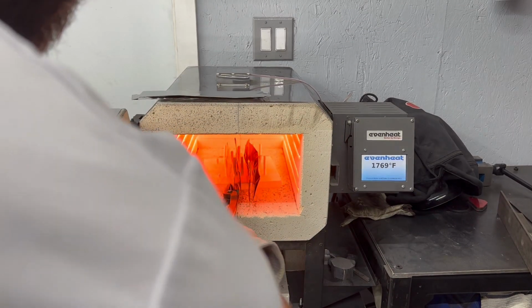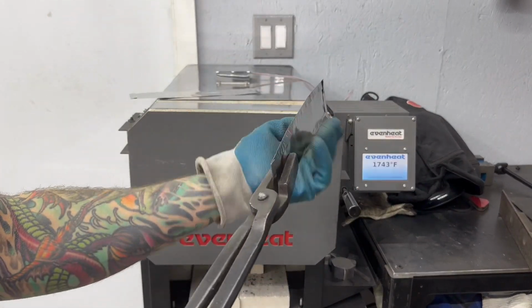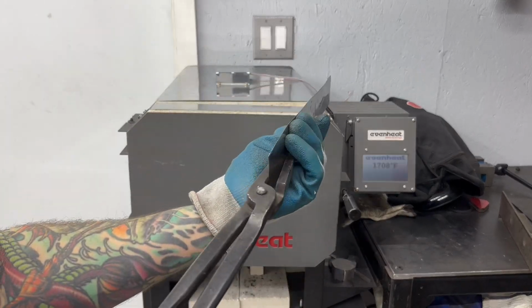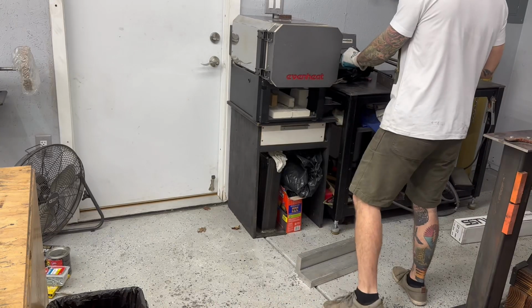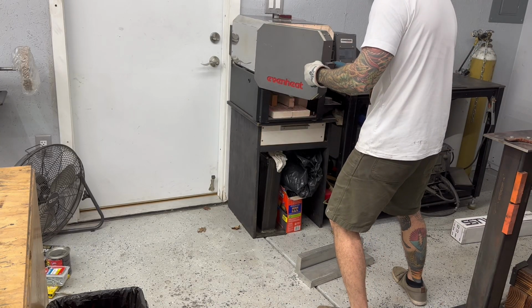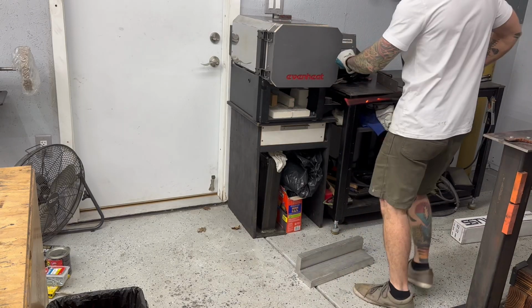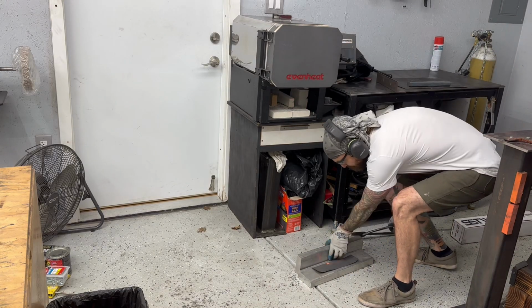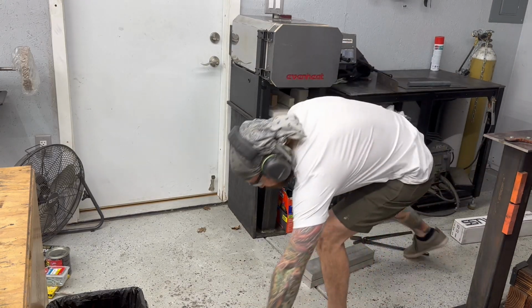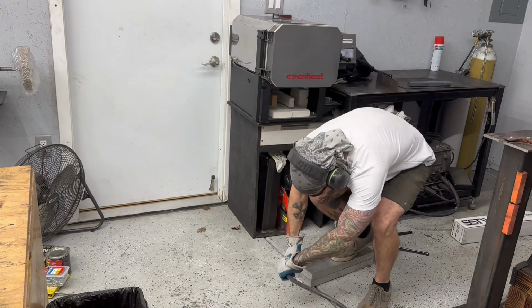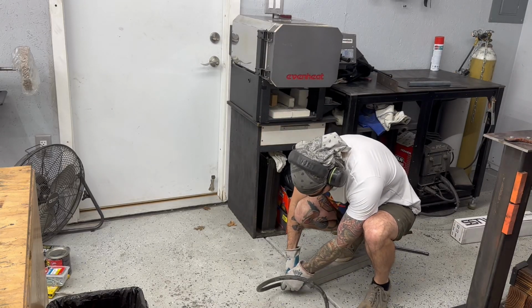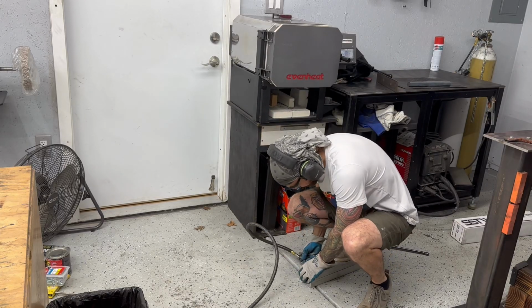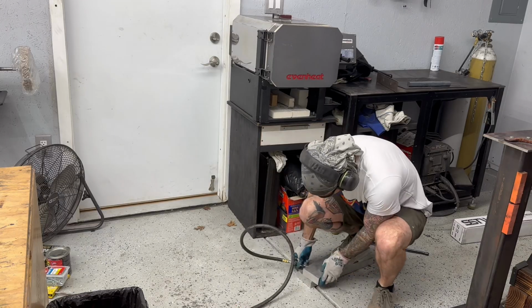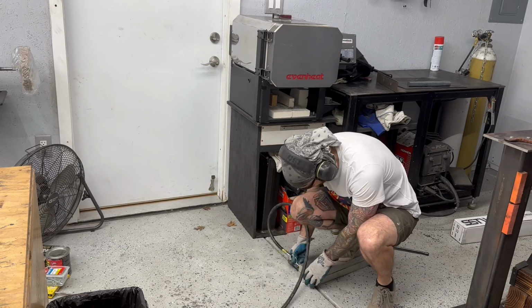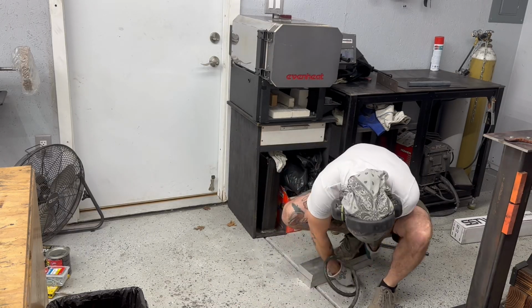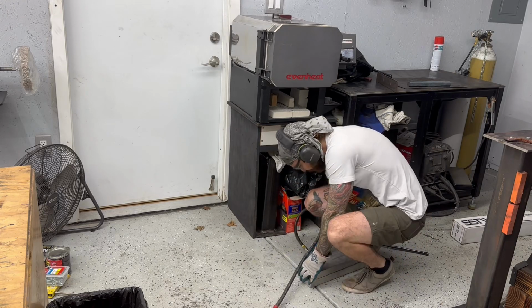And there they all are. Wait for them to get up to temperature. And then my quenching process is, this is air-cooled steel, so I just drop down in between these two aluminum plates, which helps suck the heat out and also keep it straight. Give it some foot pressure and blow with the air compressor. And that cools the steel fast enough for things to harden.